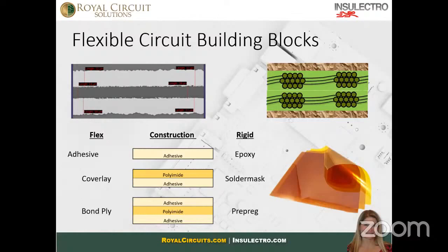So then, how do we stitch the flex cores together? What are the other building blocks besides cores that give us the flexibility we need? So instead of a solder mask as the final layer, we use coverlay. Why? Because it's flexible. It is laminated over the exposed copper cables that need to bend. Rather than prepreg being used to bond the copper cores together, we use bond plies. Coverlays and bond plies are polyimide films that are traditionally coated with an acrylic-based adhesive. The polyimide film gives us a true barrier to prevent shorting, and the adhesive allows us to glue it all together. So on the left-hand side, you can see the construction buildup of those flex materials and how they would compare to rigid building blocks when designing your rigid PCB.